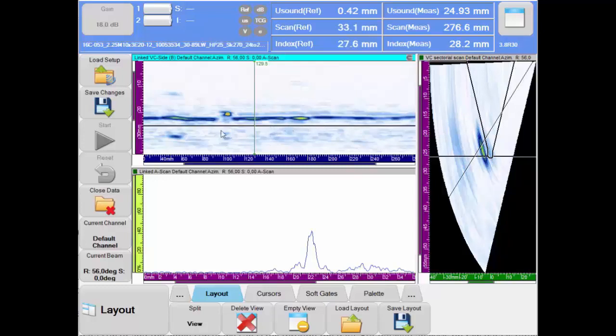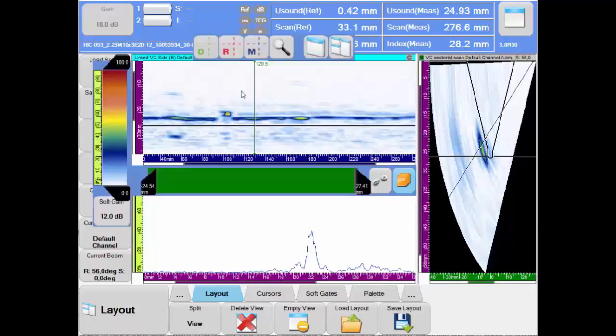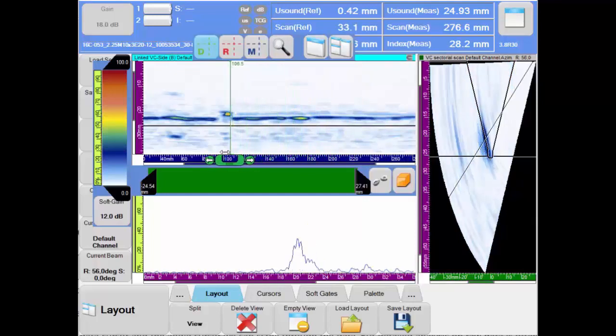Top left, we have the weld side view showing the indication depth and the position along the weld. And down left, the A-scan signal linked to the data cursor. By moving the data cursor and the angle cursor, we can scroll through the data. But detailed analysis on raw data is often a time-consuming and laborious process, especially in the case of austenitic welds due to the presence of mode-converted signals.